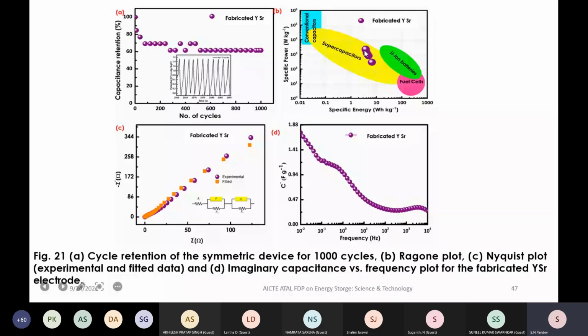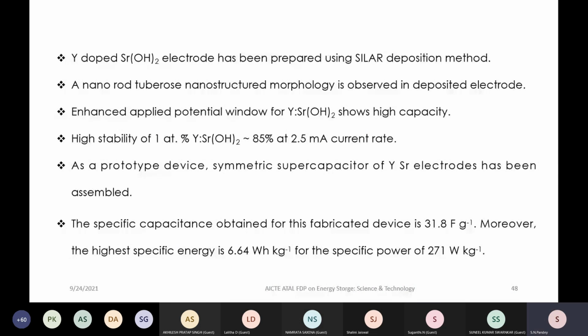So let us summarize. We have obtained YSR by the SILAR method, with a high stability of 85% for 1 atomic percent YSR. A prototype device, that is a symmetric supercapacitor where both electrodes are the same, has been assembled, and the specific capacitance obtained from the fabricated device is 31.8 farad per gram. Moreover, the highest specific energy is 6.64 watt hour per kg, for a specific power of 271 watt per kg. So let us move further.